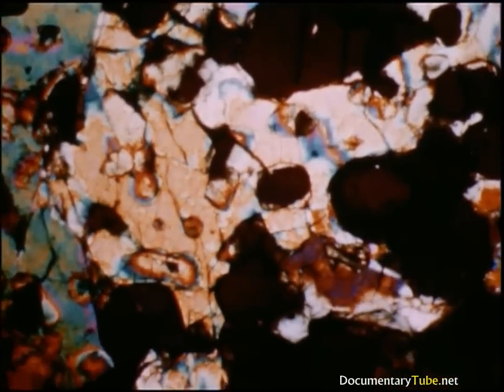High density in refractories reduces their porosity. This brick, cut to expose its interior after it had been soaked in red dye, shows color absorbed by the pores only faintly at the edges. Compare it with another brick of greater porosity that shows color over halfway through. Just as the denser brick absorbs less color, it absorbs less destructive slag and furnace gases. Destructive chemicals react with or flux the brick material, causing them to lose their refractory structure. This microscopic thin section shows that geometric crystalline structure is still present in this Permanente brick after more than a year's severe service in a glass furnace. A section from a test brick of average bond and density shows the ravages of destructive fluxing — the loss of refractory structure, conversion of crystal to liquid, which gradually loosens and flushes away the brick structure. This brick saw the same service as the Permanente brick.